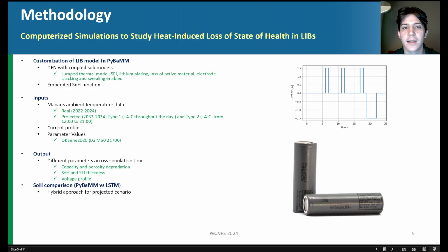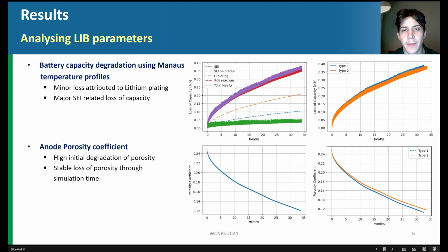The current profile simulated a realistic daily cycle, which is 3 discharges at 1.5 amps for 1 hour each, followed by a charging instance of 1.5 amps with a 3-hour duration. We use the Okane2020 parameter set, which is an LG M50 cylindrical cell. The outputs included capacity and porosity degradation, SEI layer thickness, SOH evolution, and voltage curves. Finally, the LSTM model was trained using the PyBaMM generated SOH data and used to forecast future SOH values for the projected temperature scenarios. Now for the main results.